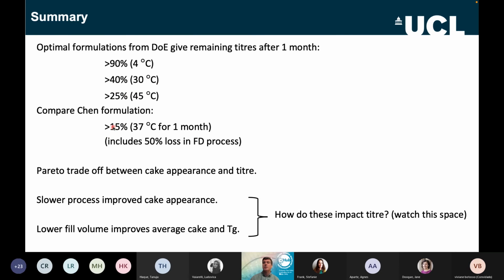When you compare the Chen formulation, at 37 degrees for a month, which is somewhere between these two, it was only 15% remaining, and most of that was lost in the freeze dryer itself. So we've gained quite a good advantage over the existing formulation in being able to store at something like 30 degrees and still get decent titer back. And these numbers will improve because of the new process as well. We had a trade-off between cake appearance and titer, but slowing the process and the gradients down appears to have improved that. The lower fill volume also appears to improve it. I've put this question mark here.